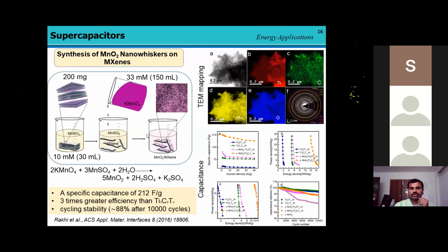Also, it has shown a specific capacitance of more than 200 farad per gram, which is 3 times higher than the pristine form of MXene, and also showed more than 88% cycling stability even after 10,000 cycles. Also, this material, the manganese oxide with MXene, was compared with the graphene-based material. Then the graphene-based material showed lesser specific capacitance than the MXene-based material.